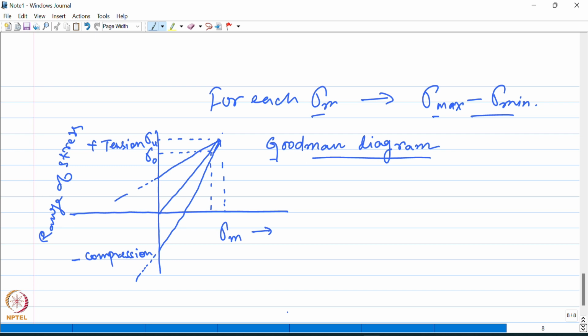Here sigma u is the ultimate tensile strength of the material, and sigma naught is the yield strength. So this plot or this relationship is obtained for a fixed number of cycles or at the fatigue limit of the material. So you can see that as the mean stress becomes more tensile, the allowable range of stress is decreasing, until it reaches the tensile strength sigma u. So that's what you see over here: as it reaches the point where the stress is equal to the ultimate tensile strength of the material, sigma r becomes 0.